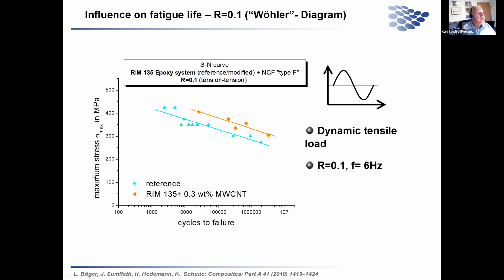Here we have plotted the maximum stress in a load cycle versus the number of cycles to failure. What we can see is a test with fiber reinforced material without any nanoparticles in the matrix. If we add nanoparticles to the matrix, we see an improvement in fatigue life.